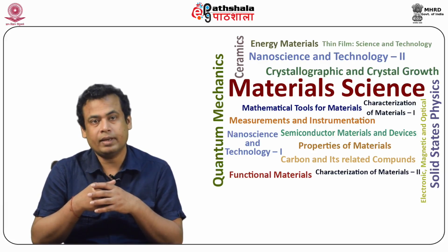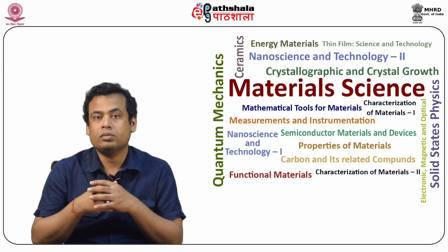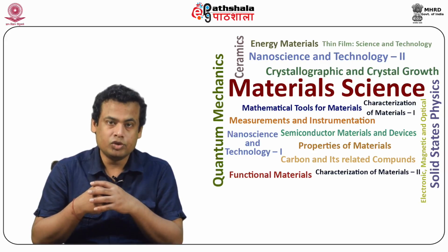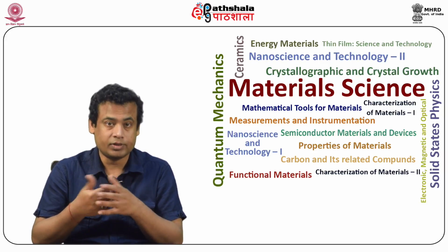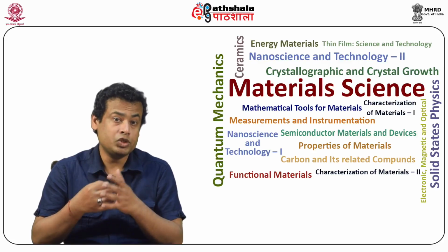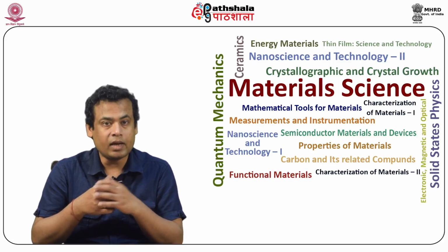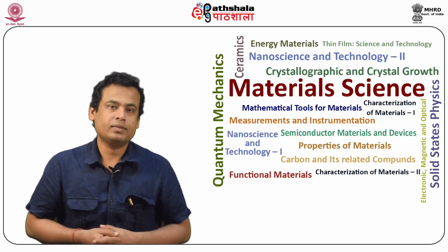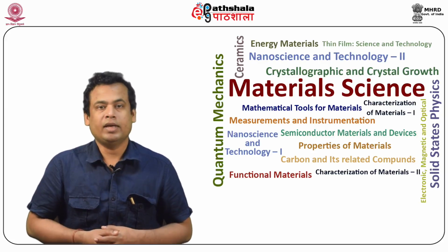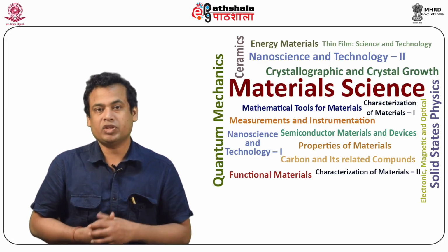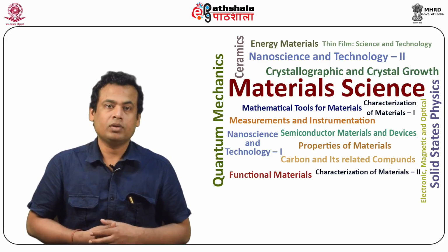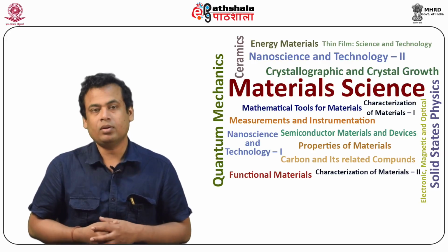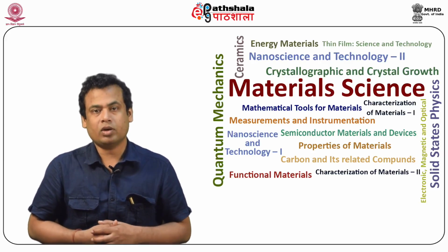The number of secondary electrons can be greater than the number of incoming electrons. They are used to reveal the surface structure of a material with a resolution of about 10 nanometers or better. The secondary electron coefficient is defined as delta equal to NSE divided by NB, that means the ratio of the number of secondary electrons from the specimen divided by the number of beam electrons incident on the specimen.